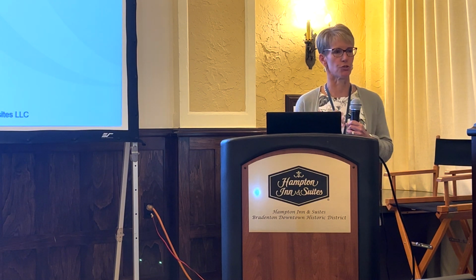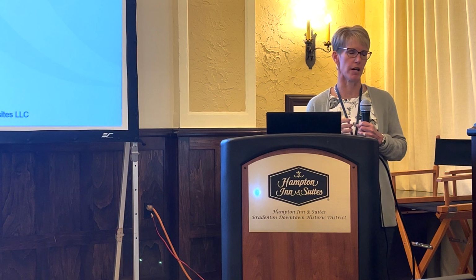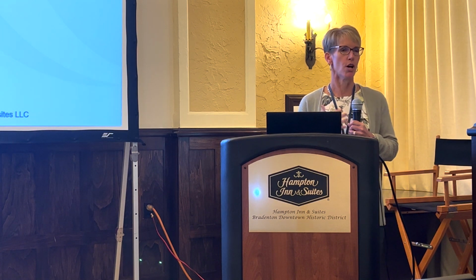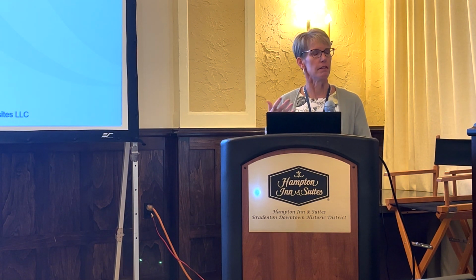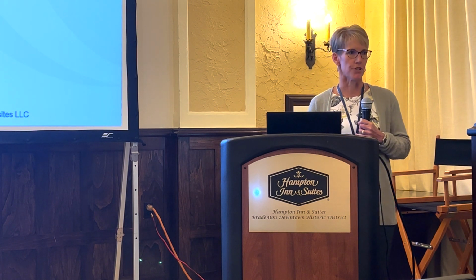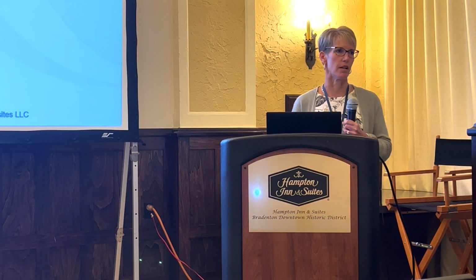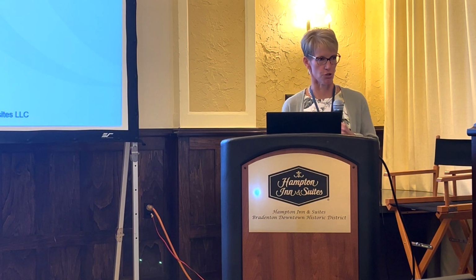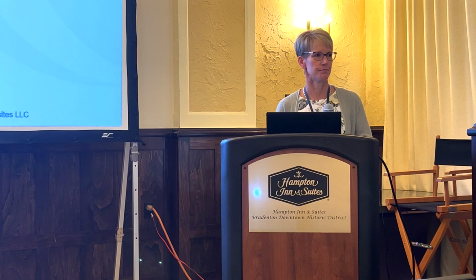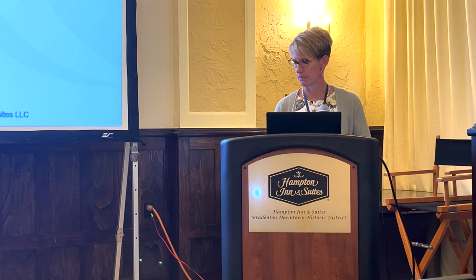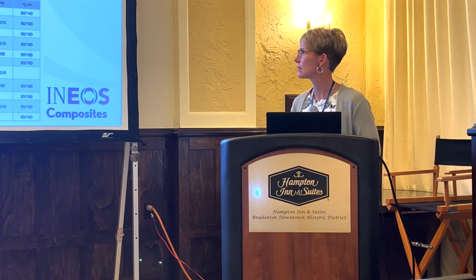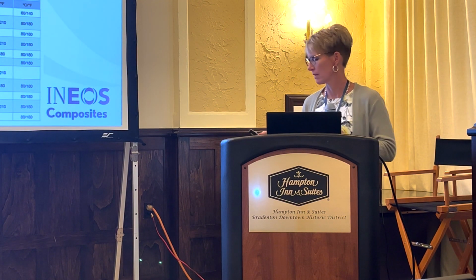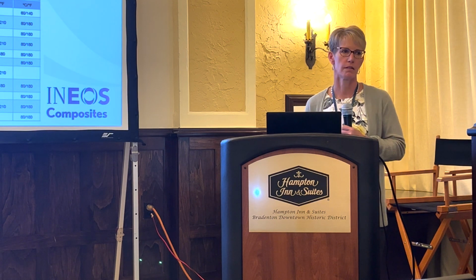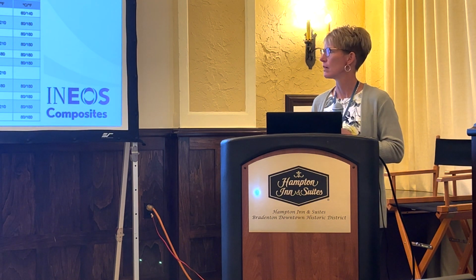What we've found is certainly you don't want to use the C glass veil because the fluoride does attack the C glass veil. But with a synthetic veil, say in hydrochloric acid, generally your Derakane 470 with a synthetic veil will provide you with a good service life, up to a certain concentration, which is in our guide. There is a maximum concentration that we recommend. I think it's about 30% concentration is the maximum for hydrochloric acid.